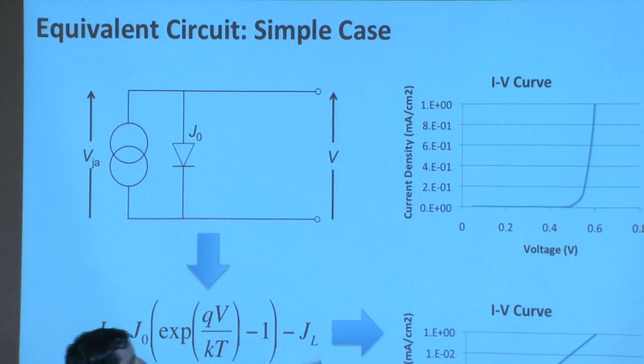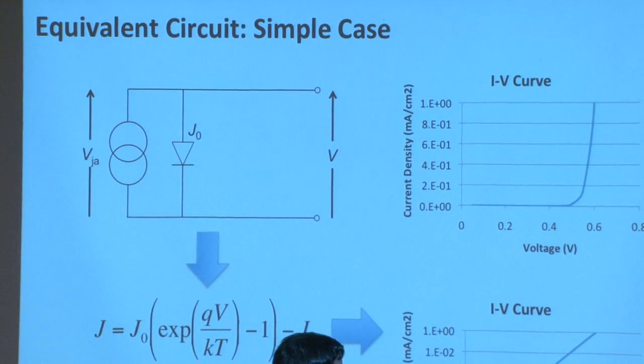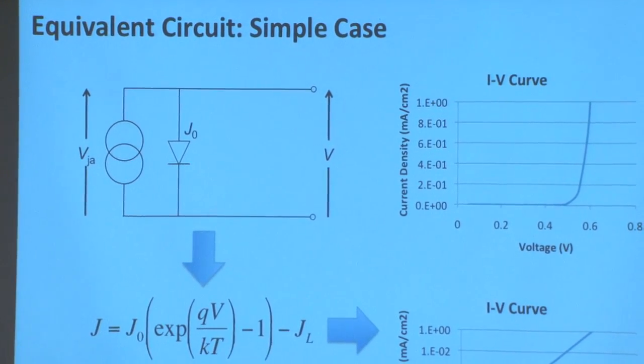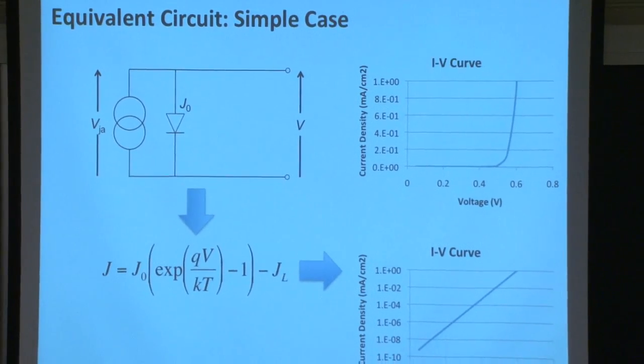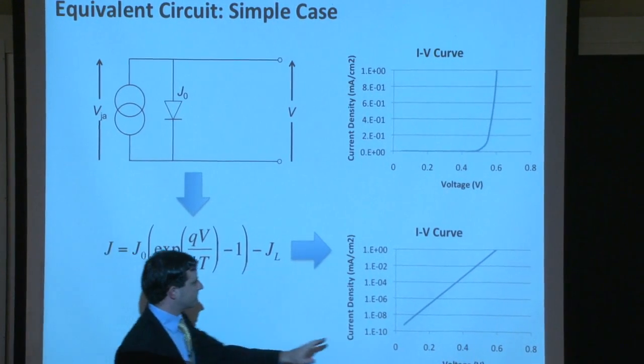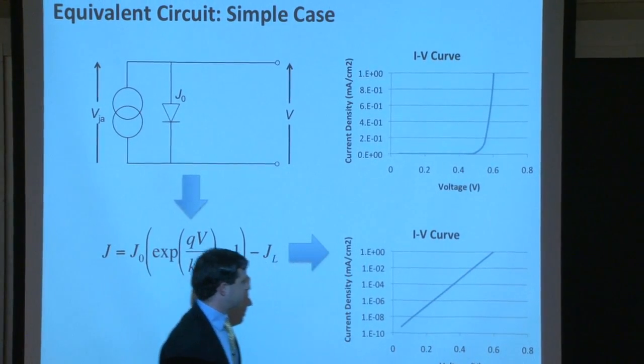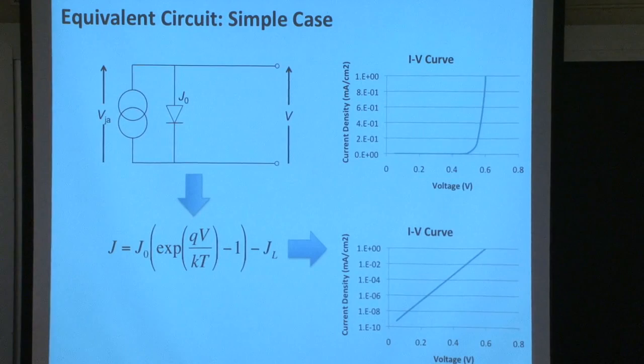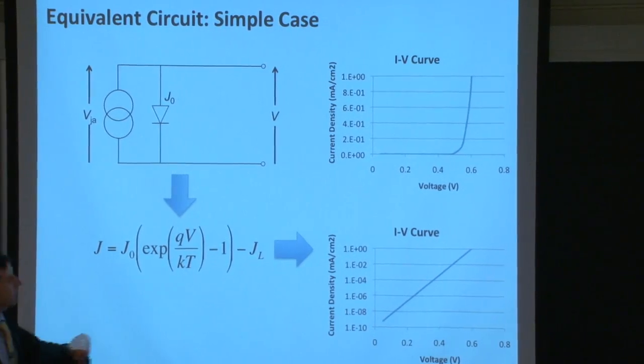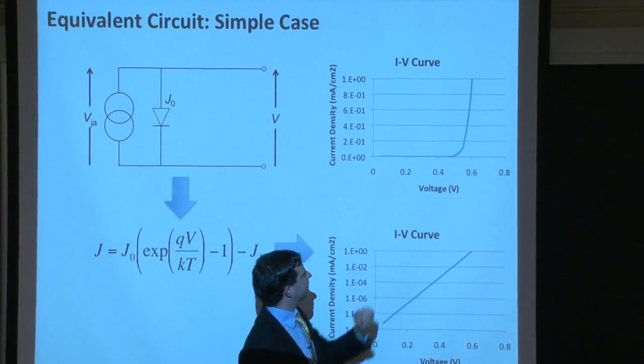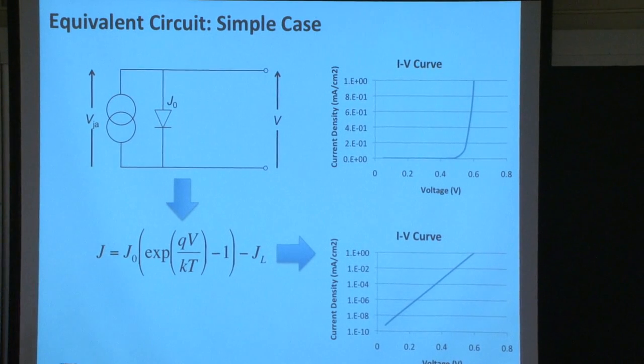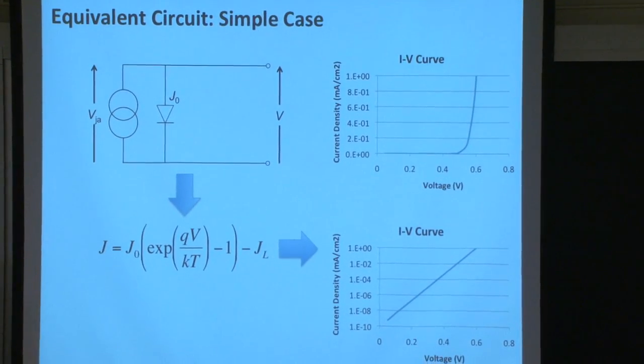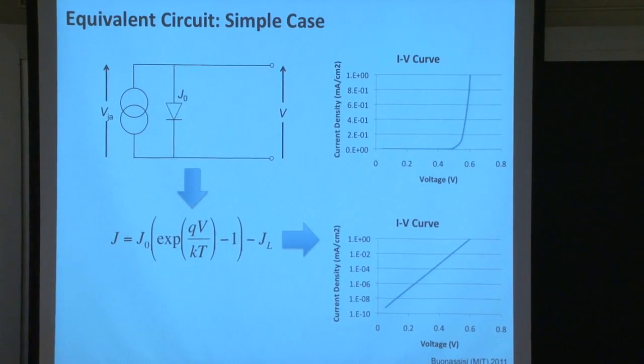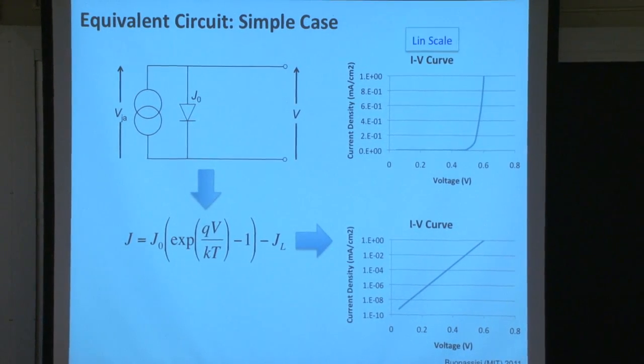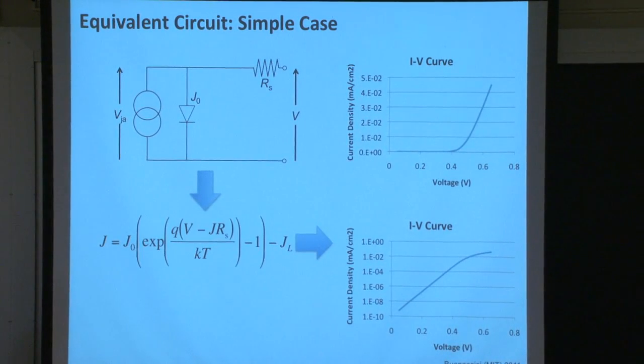And we can see our IV curve in linear scale and log linear scale there, log current, linear voltage. And because this is an exponential, you would expect a straight line, and you do see that indeed. Now, the IV curve in the upper part, you can really see has a very nice fill factor, as a very sharp kink pops straight up. And so the fill factor of that IV curve, when illuminated, will be very high, and hence the solar cell efficiency will be high.